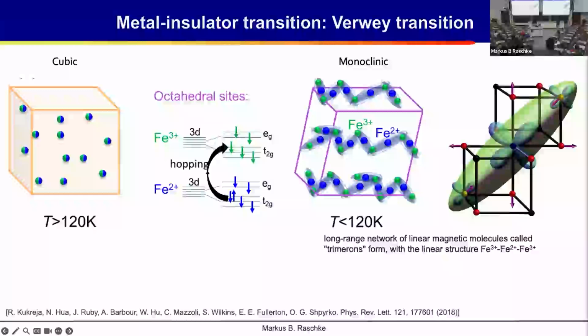And so above 120 Kelvin, so at room temperature, and this is this crystal, I asked it this morning, it confirmed that I'm in a cubic phase. You can actually see the cubic structure. If you want to come up later, you see the symmetric crystal faces. Yeah, so this is cubic.